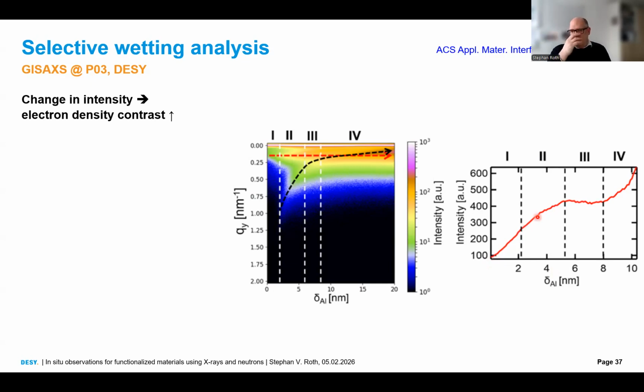Well, the polymer doesn't change, but what changes is that the aluminum grows selectively on one block. So you increase the electron density difference between the two blocks of the diblock copolymer. It grows on P3HT and not on PMMA. So I have here something like polymer plus aluminum versus polymer, and it increases.